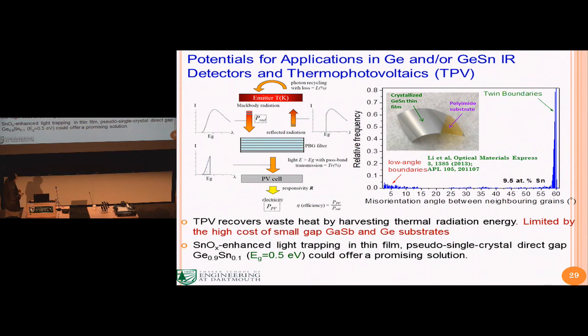And this can be further extended to our applications in thermal photovoltaics. As we know, there are a lot of places generating a lot of heat, and that heat is basically wasted. So if you can recover part of that, that's a big boost to energy efficiency. Because the heat source usually radiates infrared, you have to use small bandgap semiconductors like gallium antimonide and germanium. But those, again, are very expensive. However, now we have the high crystallinity germanium tin on glass or plastic substrate. We can further couple this with light trapping using the tin monoxide, and potentially achieve very efficient thermal photovoltaic cells.